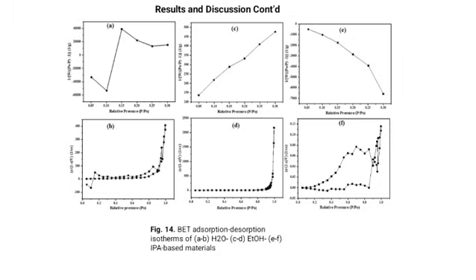For the BET surface properties of the material, it was observed that the material demonstrated a type 2 and type 4 isotherm, which is typical for non-porous or macroporous materials. Moreover, the materials displayed a hysteresis loop due to unrestricted mono-multilayer adsorption.